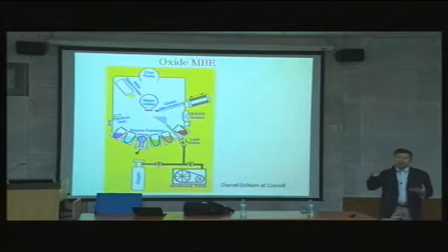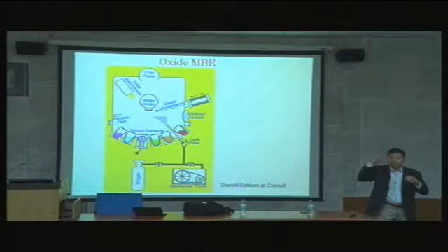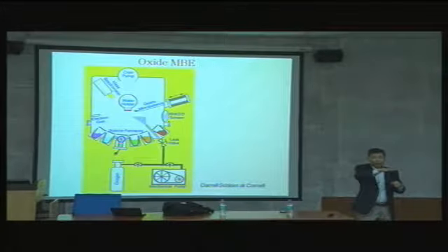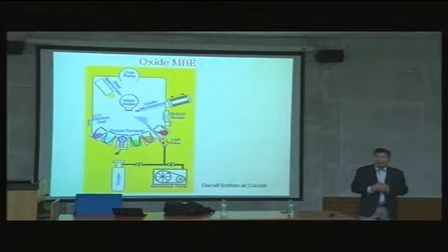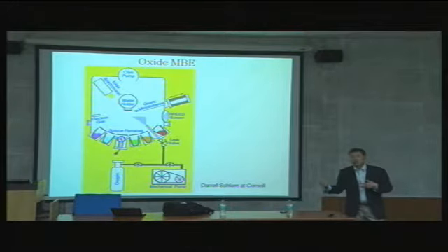I can put down the strontium layer only, then the titanium layer only. So I can grow unit cell by unit cell. It's like one packed unit cell, which means a strontium oxide layer and a titanium oxide layer, you can grow with individual layer control. And that allows you to grow strontium titanate epitaxially on silicon, and we'll talk about that next